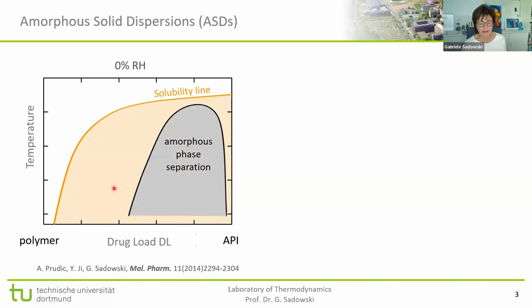But on top of this, there might also be a liquid-liquid phase separation, or an LLE, and pharmaceutic people call this amorphous phase separation. We thermodynamicists would call this an LLE, and this can also happen for those systems. So the best thing for a tablet means stay outside, because this means that we are at those concentration and temperature areas where the system is not supersaturated, it's thermodynamically stable. The bad thing is usually the temperature we are dealing with, body or storage temperature, is far below the